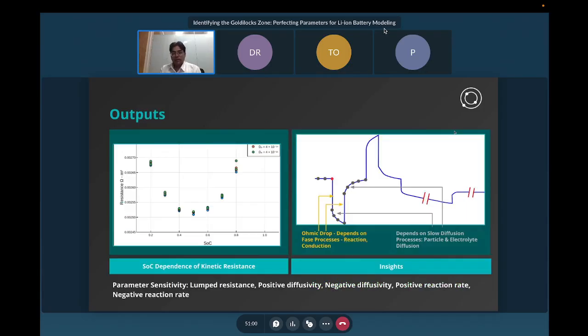Now, as an output, because I mentioned earlier that for each pulse we are optimizing these parameters, you will get the SOC dependence for these parameters. Here is one example for the internal resistance, where you would see that at SOC 0.5 you have the lump resistance which is minimal, and as you go to higher or lower SOCs, the lump resistance increases. And here we are also trying to show that even if you have different kinds of diffusivities, the lump resistance value does not get impacted by the diffusivity, and you will see that each of these numbers has come to the same place.